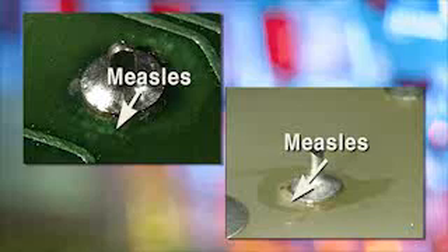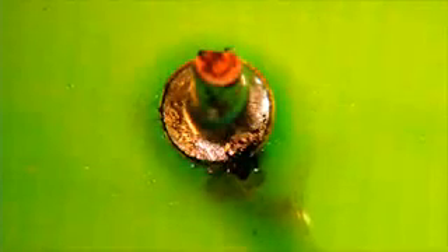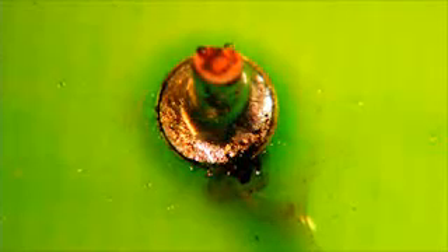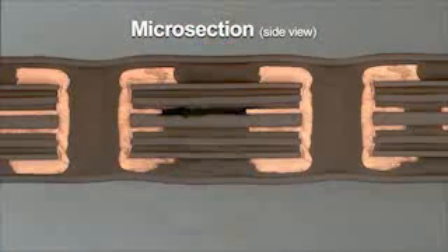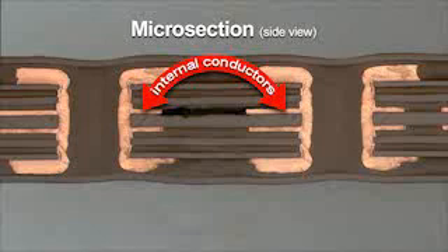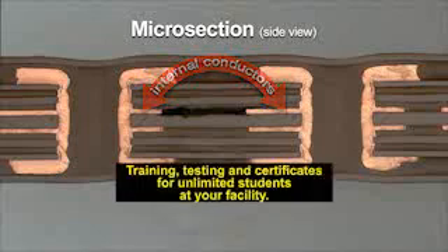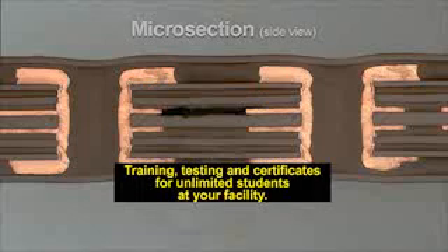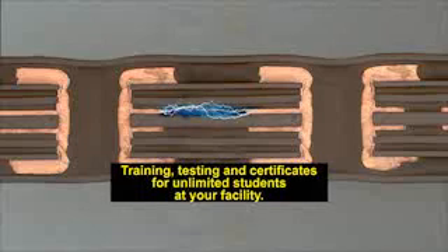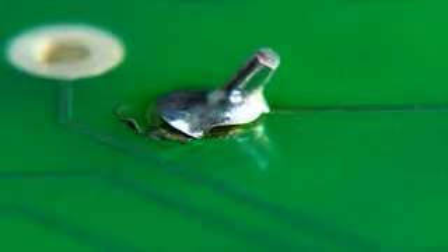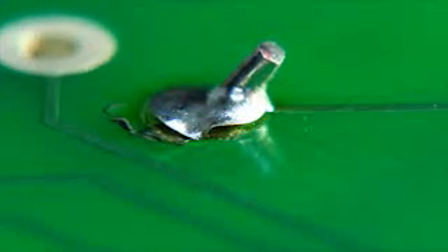Measles are not a cause for rejection. Heat damage can cause internal delamination of the base material. Internal delamination is where two layers separate, creating a void. If there happens to be any internal conductors within this delaminated area, there will be little or no electrical insulation between them. In high humidity environments, delamination can result in electrical problems. Excess heat can also separate or lift the land from the base material.